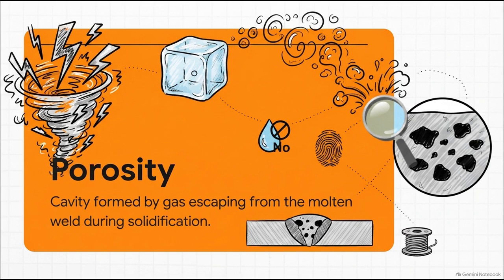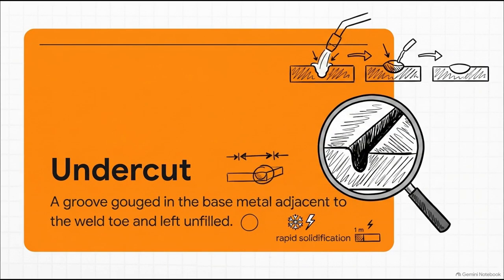The first major enemy we face is porosity. I want you to imagine a microscopic bubble of air trapped in a freezing ice cube. That is exactly what is happening here, but with molten steel. As the metal cools and solidifies, trapped gases are frantically trying to escape. If they can't get out in time, they leave permanent cavities inside or right on the surface of the weld. This is typically caused by moisture, a dirty base metal, or a contaminated wire. It can be scattered all over, clustered up, or form in a straight line, but make no mistake, it always weakens the joint.